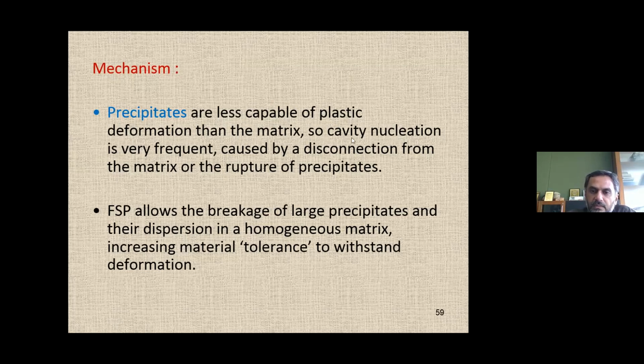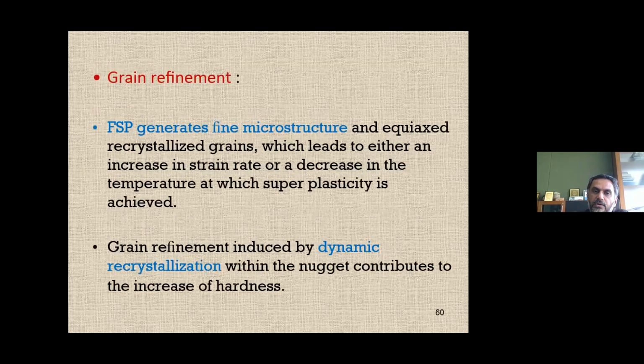And because of that, there is a possibility of cavity nucleation, which is very frequent. You may get cavities because you have two different materials, one is precipitate and another one is the matrix, and both are deformed at the same parameters. So because of the difference in the deformation trend, you may get cavities. And FSP allows you to break off these large precipitates and disperse them in the matrix. Because of friction stir processing, those precipitates get fragmented and distributed very uniformly into the material. That is one of the reasons, since those precipitates also restrict the dislocation movement, that you will get very good elongation. So one particular reason is the precipitate.